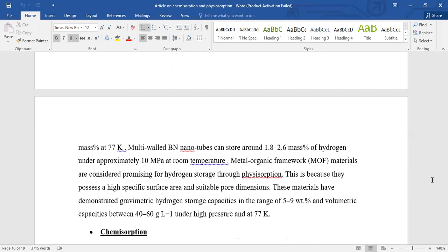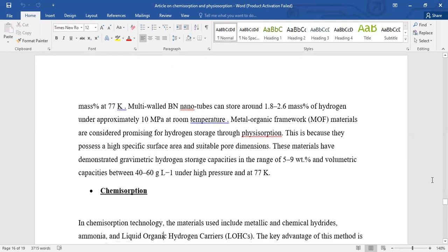This is because they possess a high specific surface area and suitable pore dimension. These materials have demonstrated gravimetric hydrogen storage capacity in the range of 5 to 9% weight and volumetric capacities between 40 to 60 grams per liter under high pressure and at 77 Kelvin.